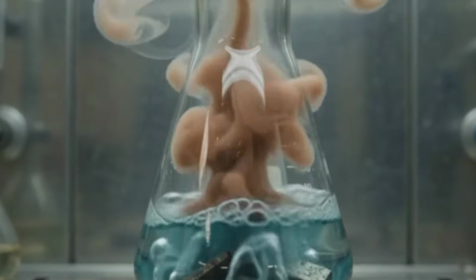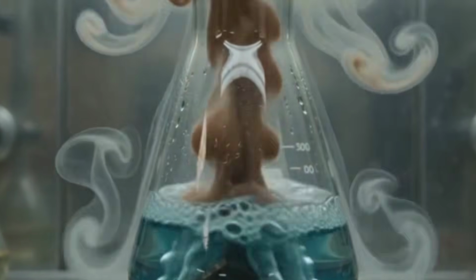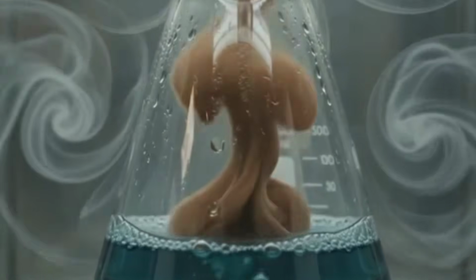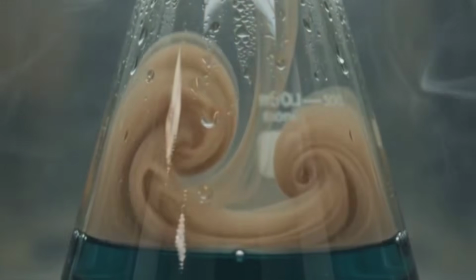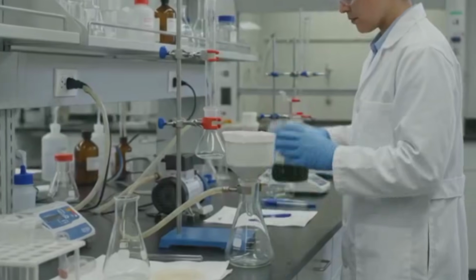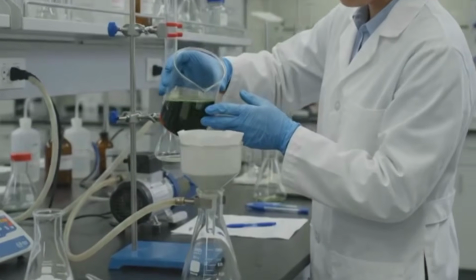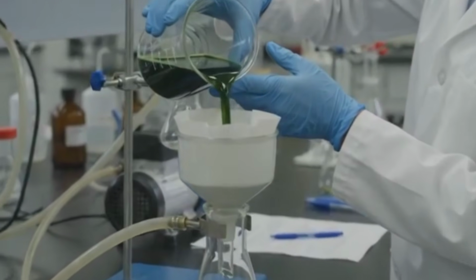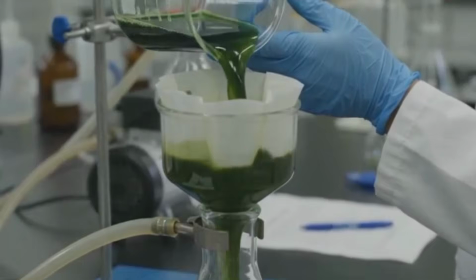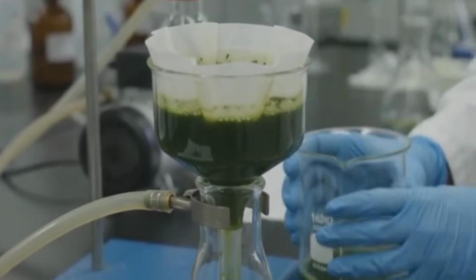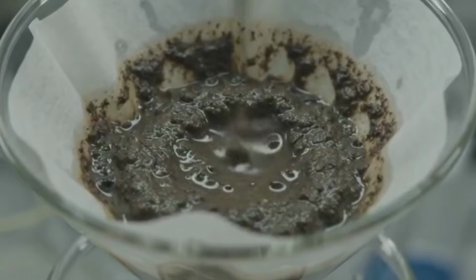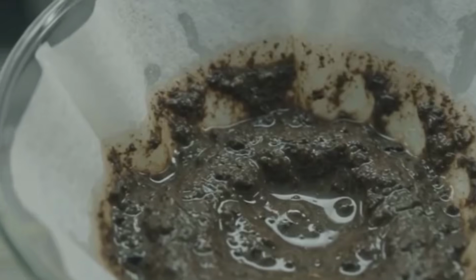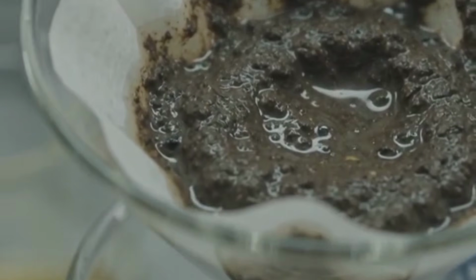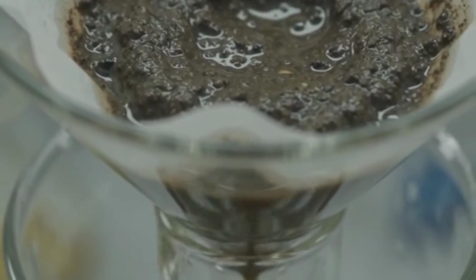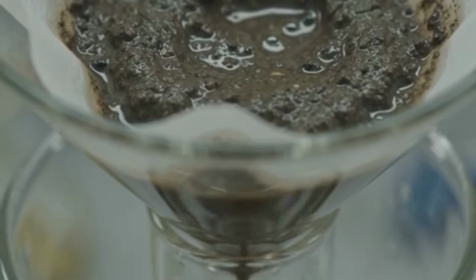A violent reaction occurs as the base metals dissolve, turning the liquid into a rich copper nitrate solution. The solution is filtered to separate the dissolved base metals from the solid, gold-bearing residue. This dark, unappealing mud contains all the gold, now completely separated from the copper and iron.